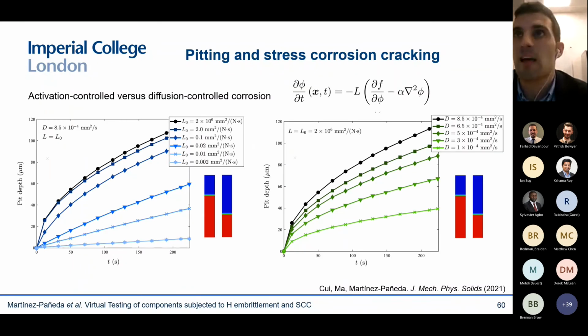And I'm just showing here in the slide very briefly that the model can capture activation control corrosion and diffusion control corrosion and the transition from one to the other. And this is captured through this mobility parameter here, which can be quantitatively related to the current density. So everything is physically based, and everything gives me physically based results. And you can see here that if you plot the pit depth versus time, you get a linear relation for activation control corrosion, but as you increase the current density, then eventually you get diffusion control corrosion. When reactions are happening sufficiently fast, the diffusion becomes the dominant mechanism. And when you are in that regime, of course, then you see an influence of the diffusion coefficient.